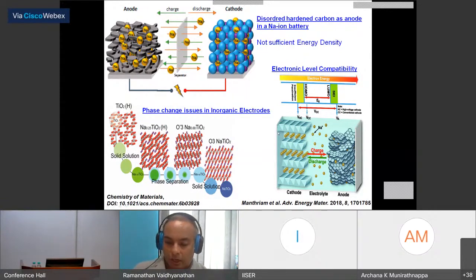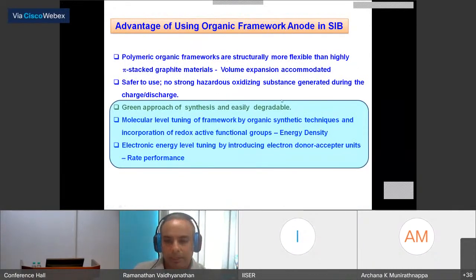And a very interesting article came from Professor Manthiram's group, where they very nicely explain how you can modulate the HOMO-LUMO gap of the anode to match the electrolyte's sodium source. And when they match at the interface of the electrolyte and the anode, if you can match the HOMO-LUMO gap to the electrolyte's HOMO-LUMO, then you will have a very ready insertion of the sodium into your anode. And also, if the gap is very favorable, then the anode can accommodate the volume expansion, provided it is made out of a flexible material. And COF being a flexible material offers you this choice of attending to the volume expansion, as well as you can functionally tune it to modulate the HOMO-LUMO gap.